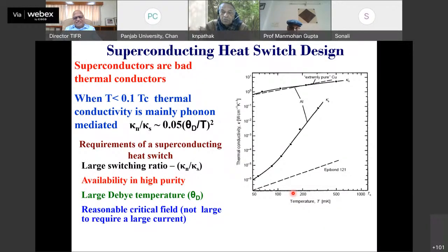And I told you that it can act as a thermal insulator, basically because you see this graph, which is the thermal conductivity as a function of temperature. You see that for copper, it still remains a good thermal conductor down to very low temperatures. Look at aluminium. Initially, they are comparable to copper, but once it starts superconducting, there is a 5 orders of magnitude reduction in the thermal conductivity. That's how it acts as an insulator.